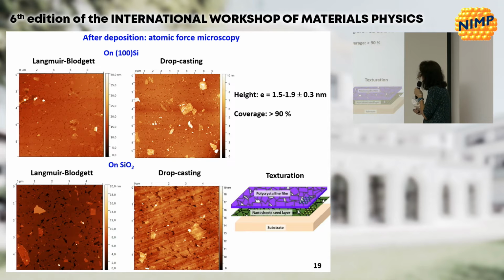But finally, we have succeeded in depositing the nanosheets by both techniques, Langmuir-Blodgett or drop casting, on silicon and on silica. And as you can see, we have a very high coverage of the substrate by the nanosheets. At some places we have two layers of nanosheets on top of each other. We can clean this by careful rubbing with a Q-tip. So the nanosheets are edge to edge, but they are not adhering in plane.